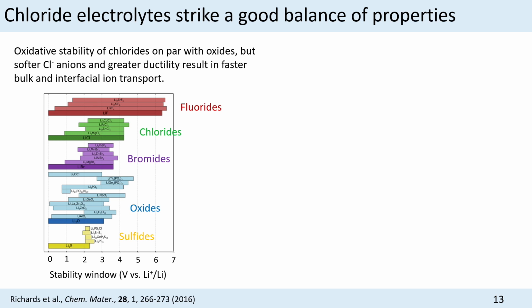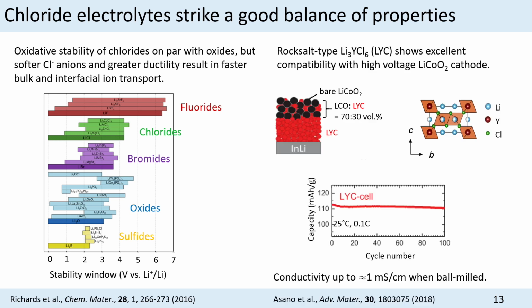But what makes chlorides unique is that they contain chlorine anions that are soft, and this imparts ductility to the material. What that means is that if you press your solid electrolyte against your electrode, you'll get a much better interfacial contact between your 2 solid materials, because one of them is ductile. And so this leads to high interfacial ion transport, which is also important when you're considering making an all-solid-state battery. These materials are of interest for lithium and for sodium-ion solid electrolytes.